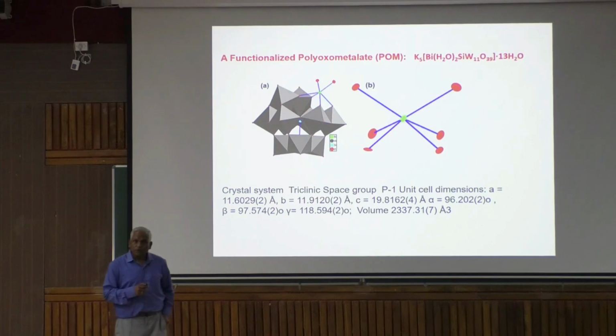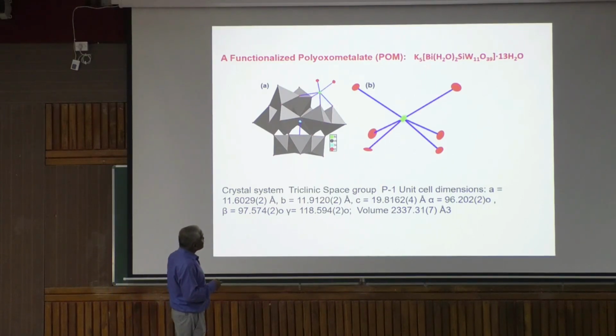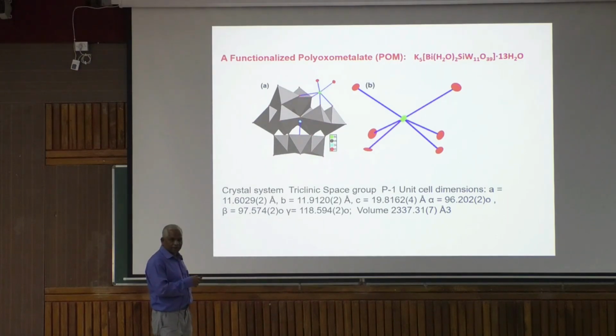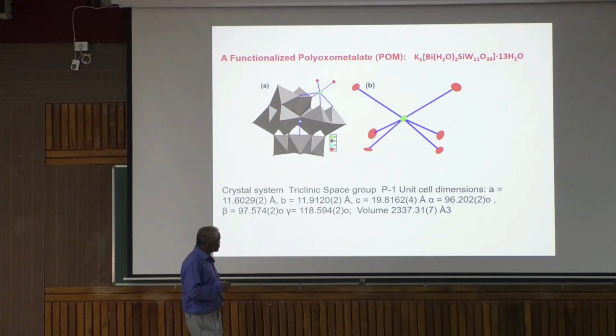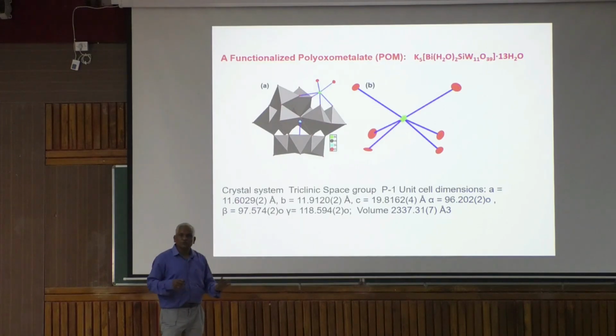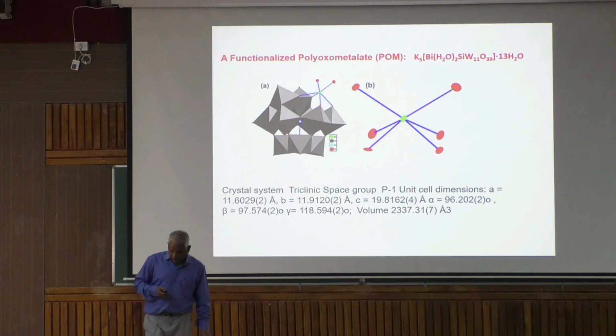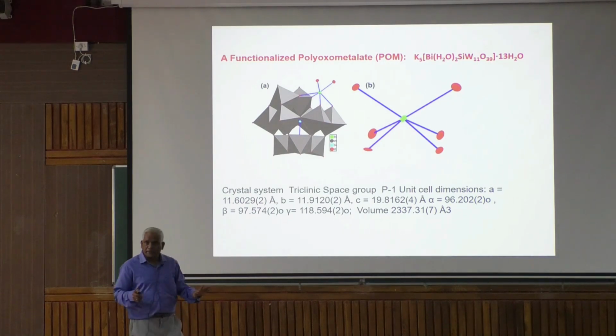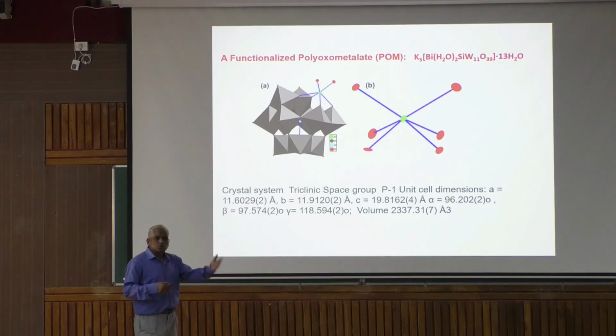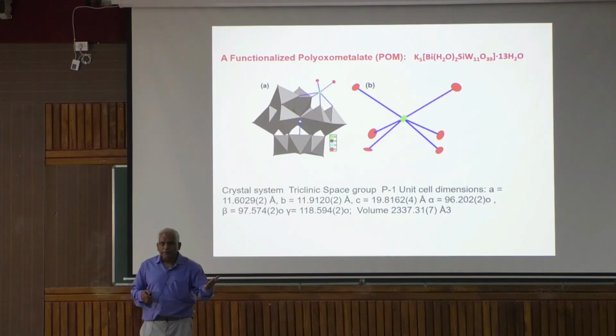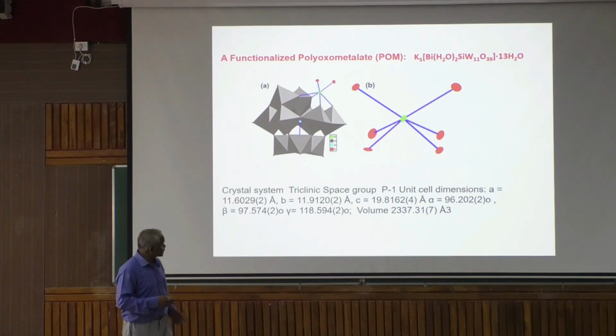Now we are lucky enough, we got the single crystal structure of this. Remember, now we are talking about bismuth in the periphery, not in the center. The center is actually silicon, but bismuth is in the periphery. So by single crystal structure we found this out, and with this compound we wanted to do some chemistry. Why? Because although silicon as such is not very active towards water splitting or anything, because bismuth is there, bismuth 3 can go to bismuth 4, can go to bismuth 5, and you can get water oxidation. So that's why we started.